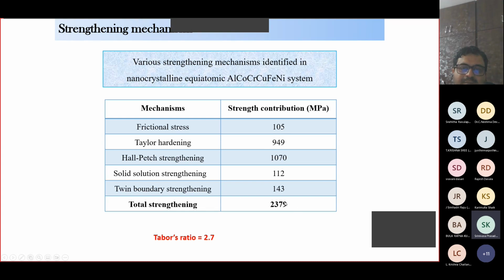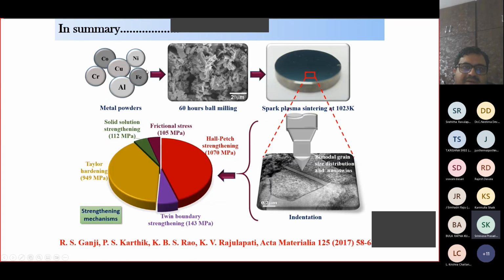And the overall strengthening is about 2.3 gigapascals. And when you look at the Taylor's constant factor, it turns out to be 2.7, which is in good agreement. And in summary, we have started with different elements in powder form. Here, the different size shows the different atomic diameter. We mill them together, and this is the grain particle morphology. We made a big disc out of it using spark plasma sintering, and we indented this using micro indentation and nano indentation. We have evaluated different strengthening mechanisms that are responsible for the high hardness, and we have published this paper in Acta Materialia in 2017, and this is a very prestigious journal.